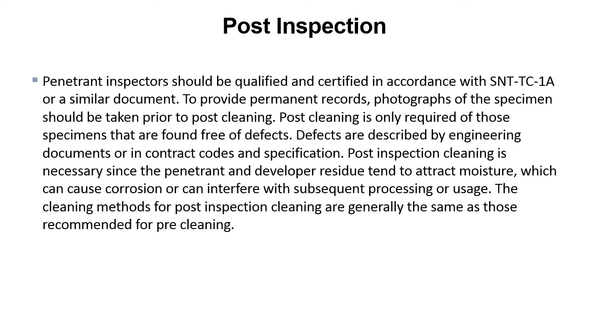Penetrant inspectors should be qualified and certified in accordance with SNT-TC1A or a similar document. To provide permanent records, photographs of the specimen should be taken prior to post-cleaning. Post-cleaning is only required for those specimens that are found free of defects. Post-inspection cleaning is necessary since the penetrant and developer residue tend to attract moisture, which can cause corrosion or can interfere with subsequent processing or usage. The cleaning methods for post-inspection cleaning are generally the same as those recommended for the pre-cleaning process.